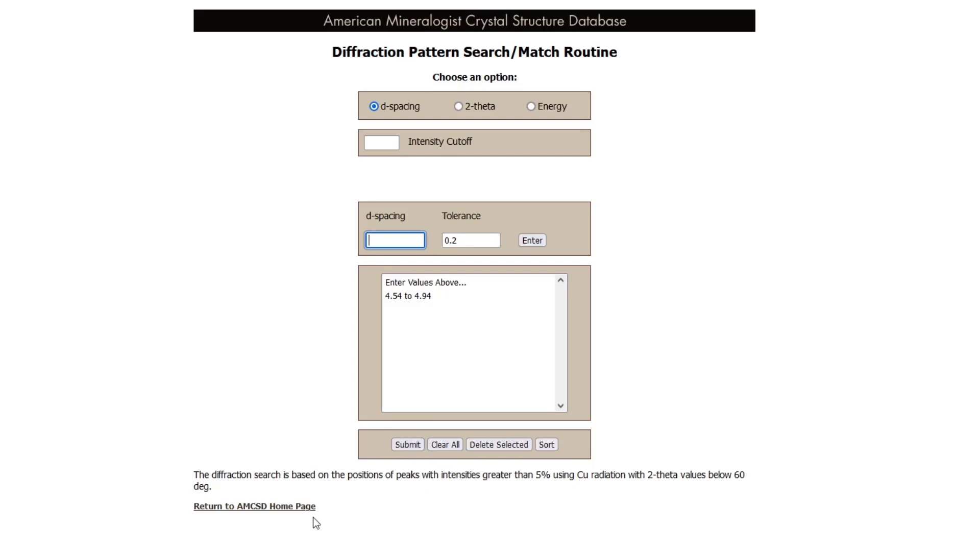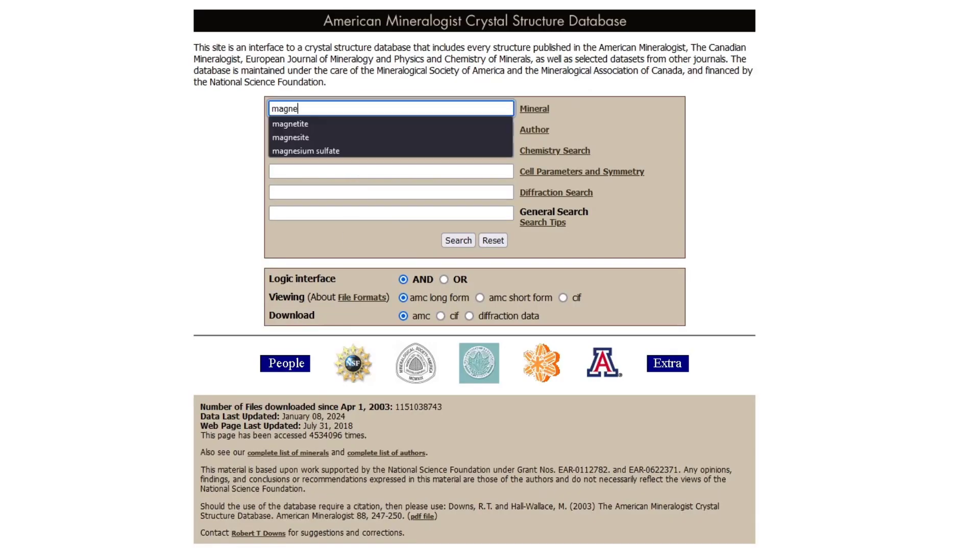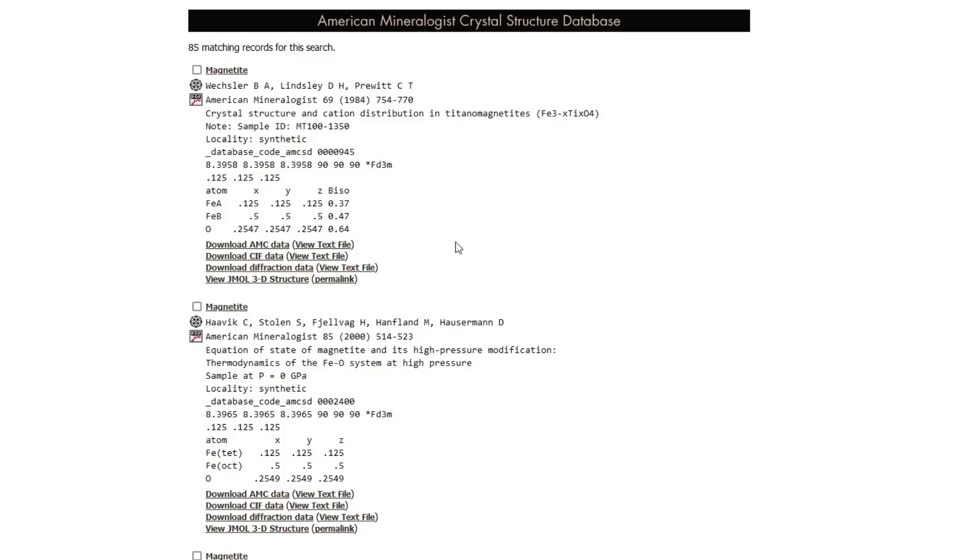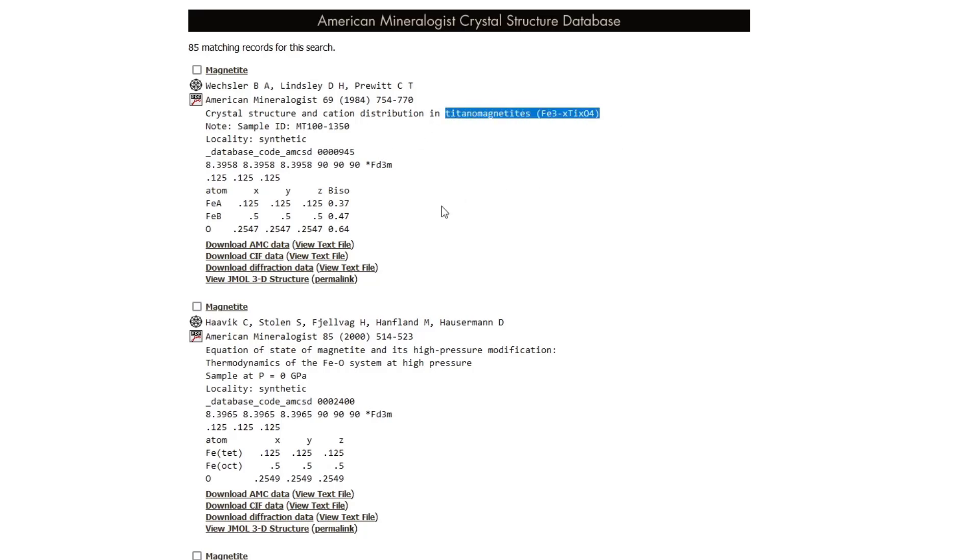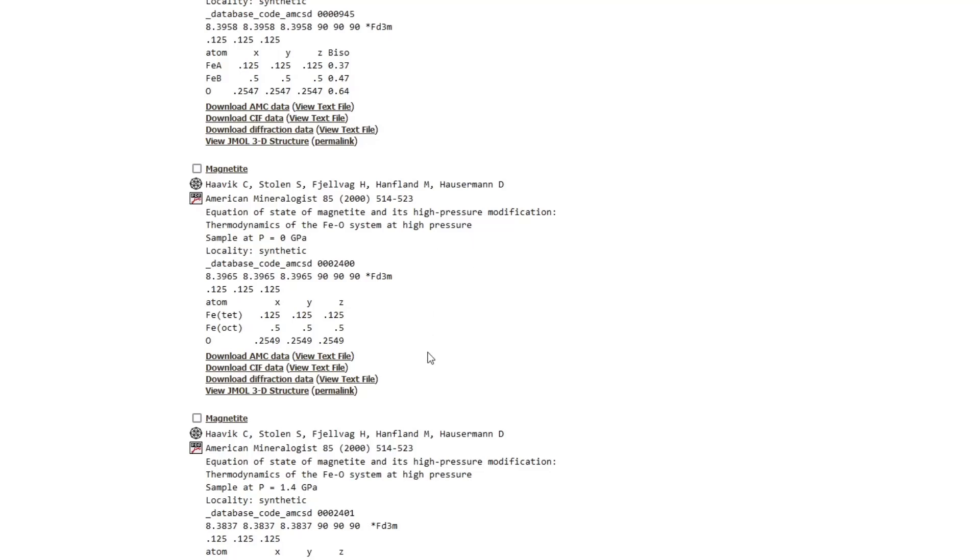You can also combine these. You can do a chemistry search with the D-spacings, but I'm going to keep it simple. I think I know what mineral this is, so I'll just type in the mineral name which is magnetite, and then I ask the system to search for me. It gives me 85 matching records. These are pulled from the literature, and you want to make sure you're using one that makes sense with your material. You might not want to use really old data. You want to make sure that the composition makes sense. I don't think mine are titanium magnetites, so that's not a good match. Pressures might be different, temperatures might be different. In this case, this is for zero gigapascal so that's fine, and you may care about if the material is synthetic or natural.